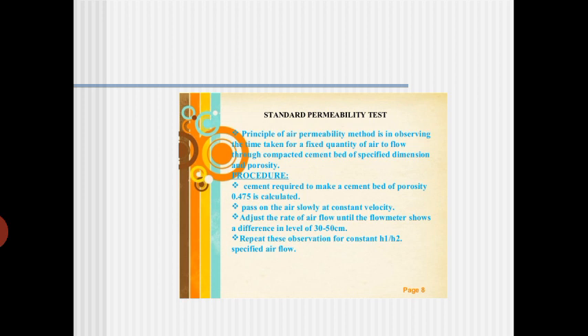So one is, it has fixed dimensions. What I said earlier is that it has fixed dimensions, a fixed thickness, and a fixed porosity. That much quantity of cement we have to take with a fixed porosity. Then what will be the procedure? The procedure is, the cement required to make a cement bed of a porosity of 0.475 is calculated. For the porosity of 0.475, we have to calculate how much quantity of cement is required. That much we have to take.